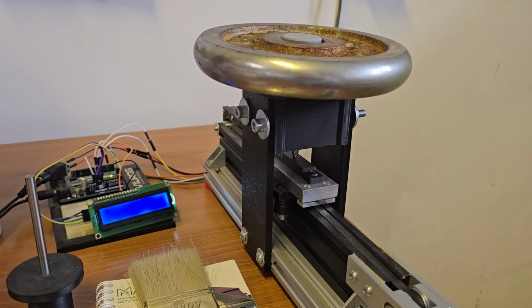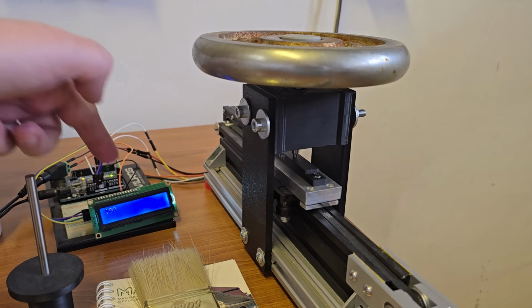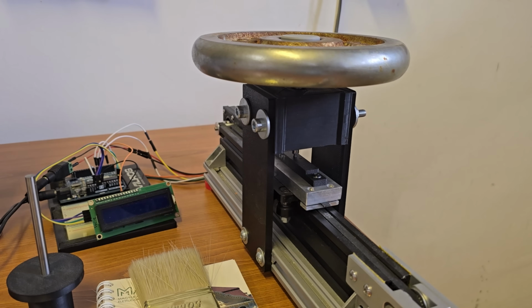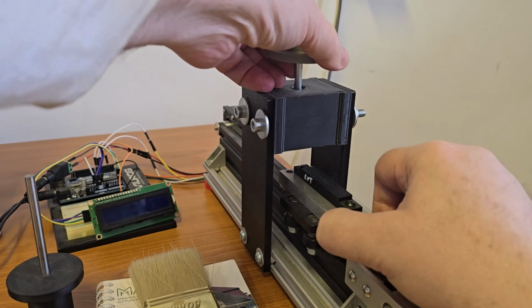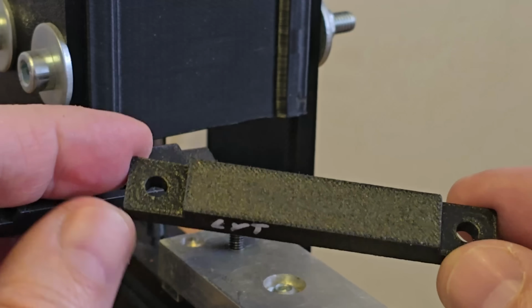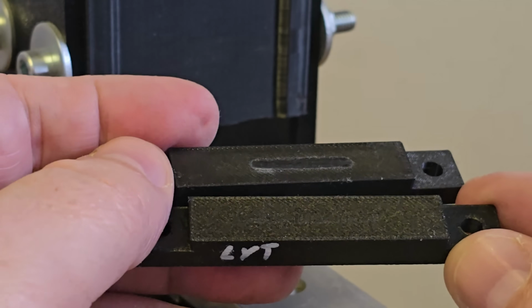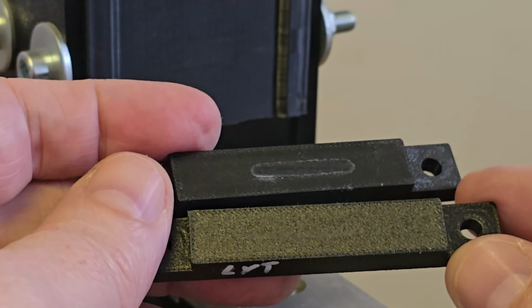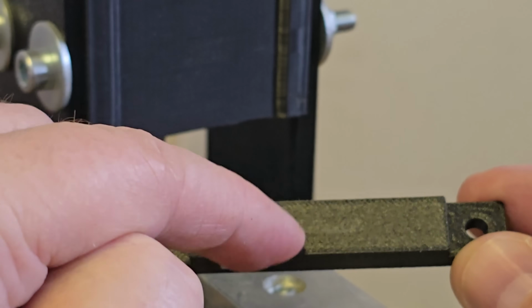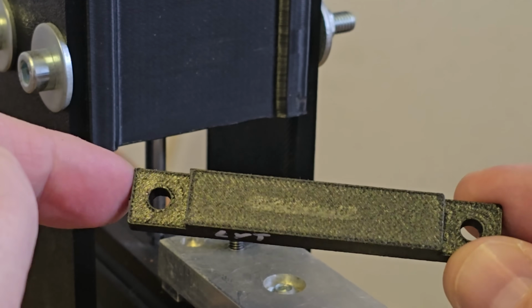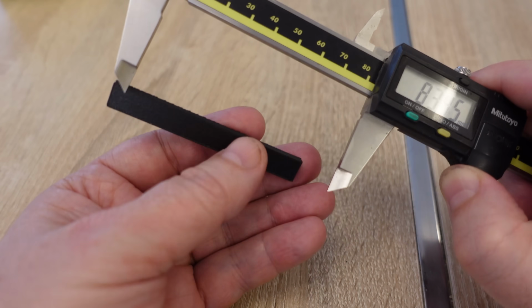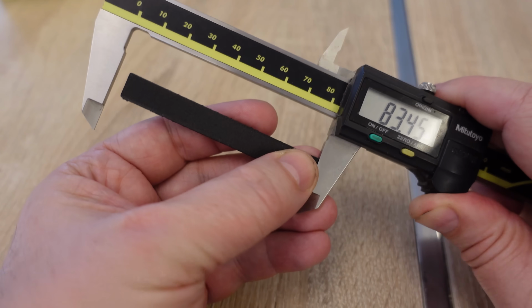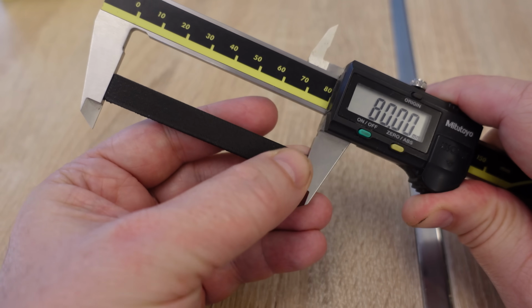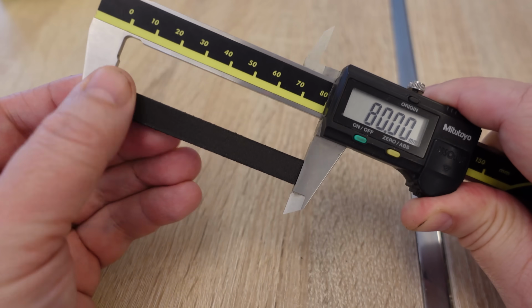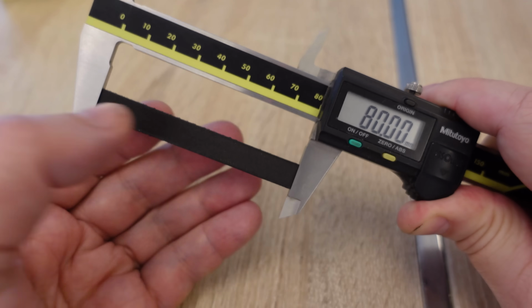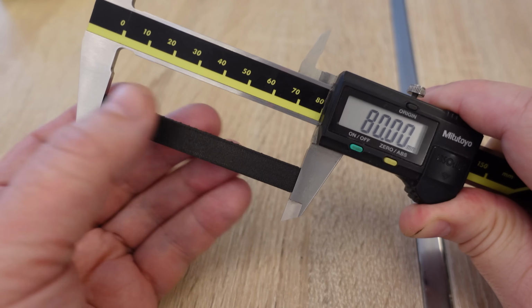My typical wearing test: shaft diameter 3 mm, 2.5 kg is the load, 200 repeats. Wear resistance not like acrylic, for example, which I tested recently, but definitely better than other nylons. Let's check the shrinking, which should be very minimal thanks to the fibers. The design length of this part is 80 mm. Quite accurate.